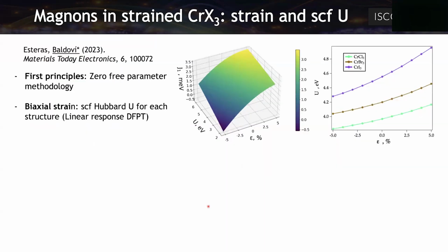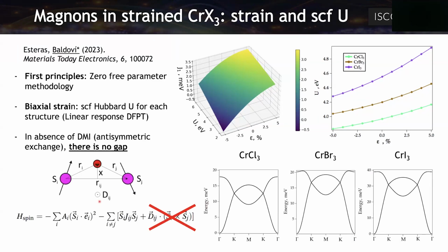We wanted to follow a fully ab initio, zero free parameter methodology in this case. So for each step in the strain, we calculate self-consistently the Hubbard-U. We are varying the Hubbard-U for the magnons because we wanted to do everything fully ab initio and test what is the effect of this Hubbard-U in the calculations. So we derive here the spin Hamiltonian for this system.